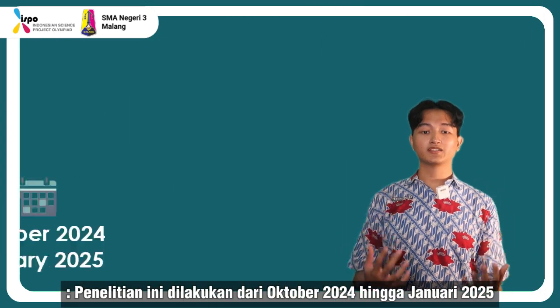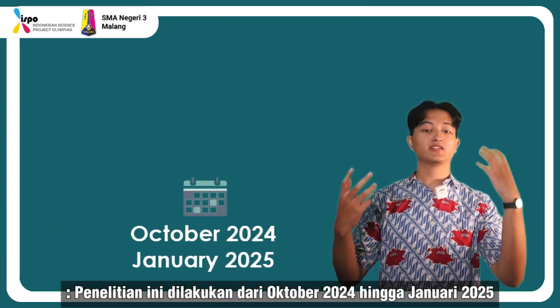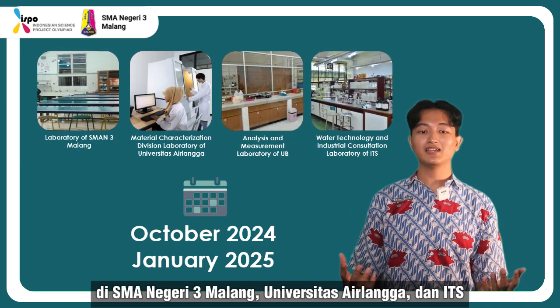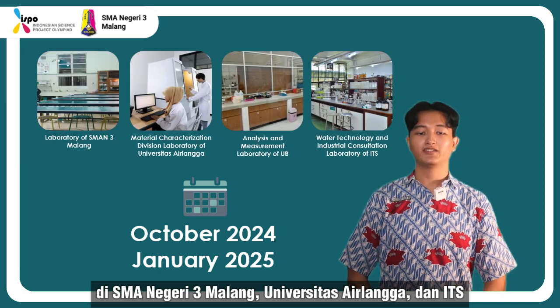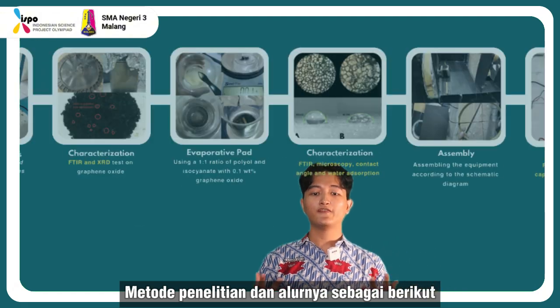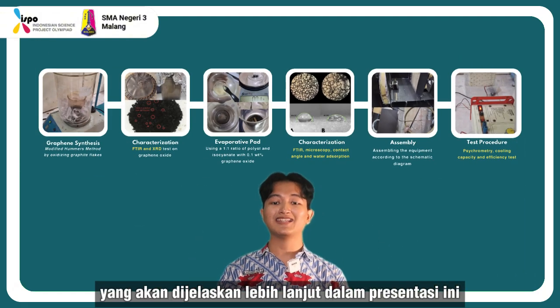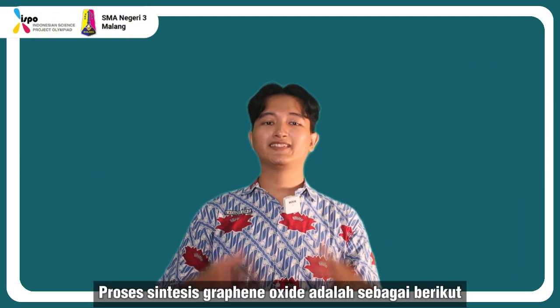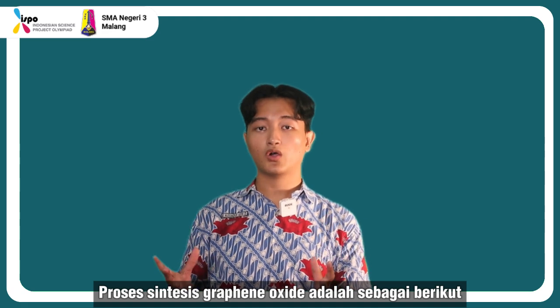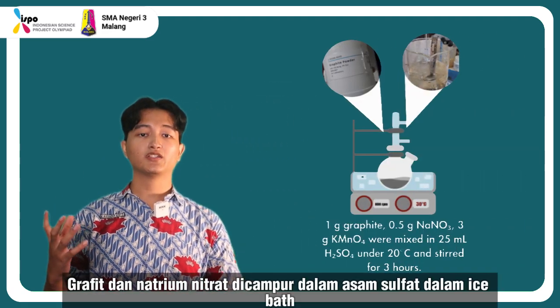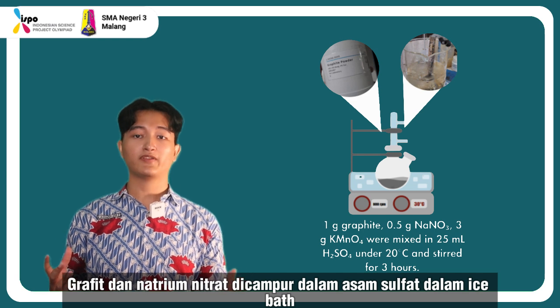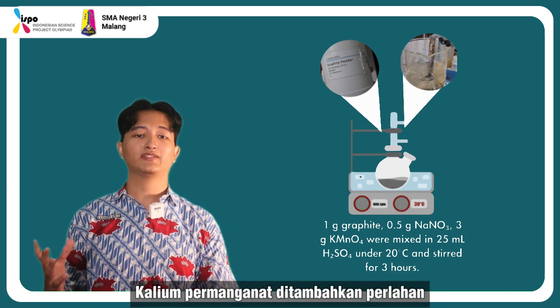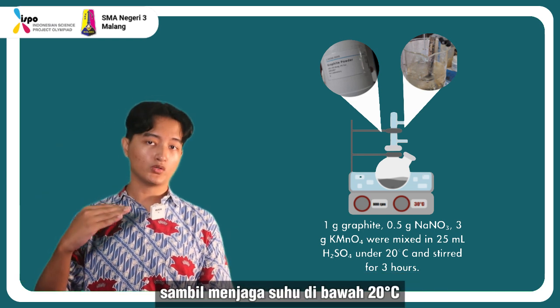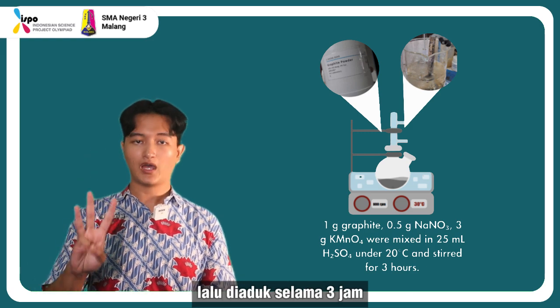Our research was conducted from October 2024 to January 2025 at SMAN Negeri 3 Malang, Airlangga University, and ITS University. The research method and flow are as shown, which will be explained in detail further in the presentation. The synthesis of graphene oxide, or GO, is as follows. Graphite and sodium nitrate were mixed in sulfuric acid with an ice bath. Potassium permanganate was added slowly, keeping the temperature below 20 degrees Celsius, and stirred for 3 hours.